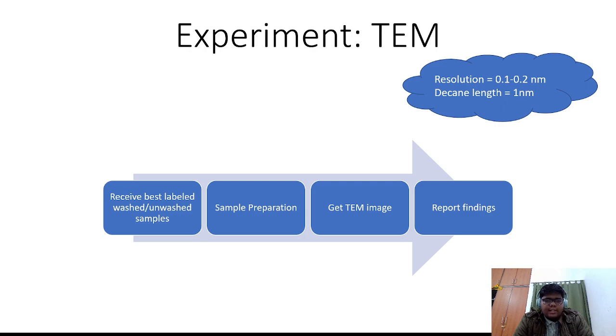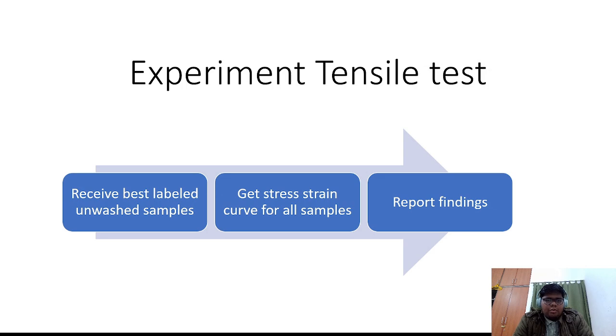Then we can take some of the best samples and do TEM: receive the best labeled washed or unwashed samples, sample preparation, get TEM image and report findings. Resolution of TEM is around 0.1 to 0.2 nanometers and decane length is 1 nanometer. So we should be able to clearly see the decane on the cotton fibers. Finally, we will have to do some tensile tests as well. So receive the best labeled unwashed samples, get stress strain curves of all samples and then report findings. This is important because of the precaution that I'll tell you later.